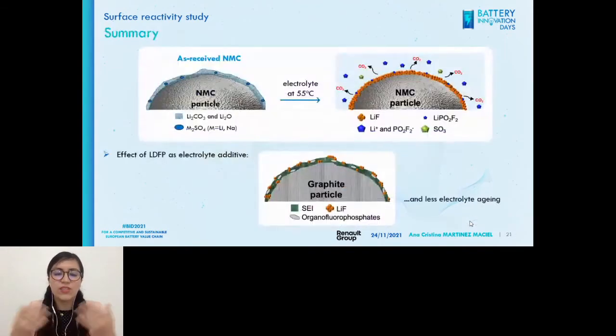As a summary of this part, the as-received materials contain the surface species we talked about. Upon exposure to the electrolyte, in battery conditions, they will produce LiF on the surface of NMC, and LiPO2F2 that can be dissolved into the electrolyte, but also can be retained on the surface, and other gases such as CO2.